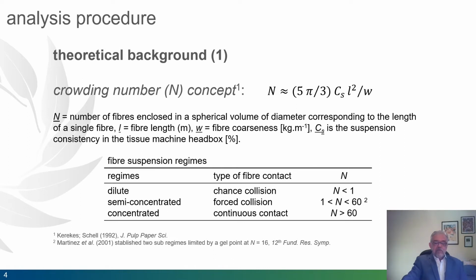The crowding number is recognized to be a good indicator of flocculation potential. The value of N defines the fiber suspension regime as shown in the table. For N less than 1, the regime is dilute and no flocculation is expected. For N greater than 1 and less than 60, the regime is semi-concentrated, where forced collision between fibers happens, and then some flocculation is expected. In concentrated regime, for N greater than 60, continuous contact between fibers usually happens, and this is the critical regime for flocculation.